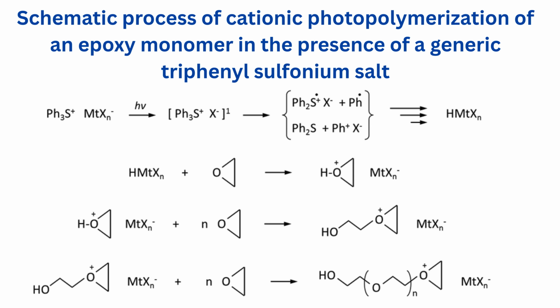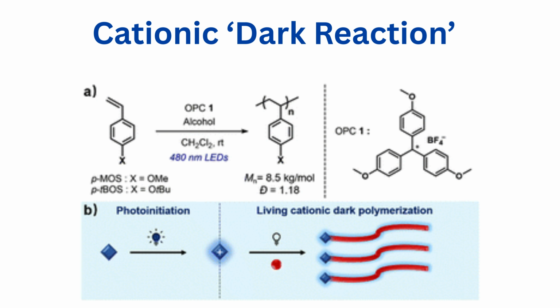Photo-initiated cationic polymerization exhibits many of the same advantages as free radical photopolymerizations. One of the main advantages of cationic systems is the absence of air inhibition, a property that eliminates the need for an inert atmosphere during curing and clearly distinguishes cationic from radical polymerization. Cationic polymerization, once initiated, is non-terminating and can continue to proceed for a considerable time after the light source has been removed. This process is generally termed a dark reaction and results in further monomer conversion, either on standing or on thermal post-treatment of a sample.